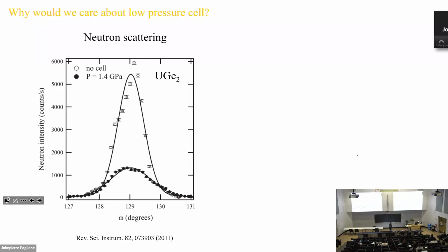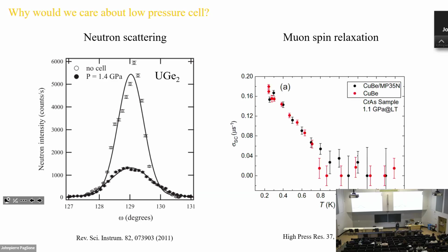And with the cell, the concern is that the neutron will attenuate. But they manage, we're going to talk about this later on, they manage so that even within the pressure cell, the intensity doesn't reduce dramatically. There is attenuation, but it's okay. Possible for experiment. Another one is μSR. You also need a large crystal, and that's possible with a piston cylinder cell.